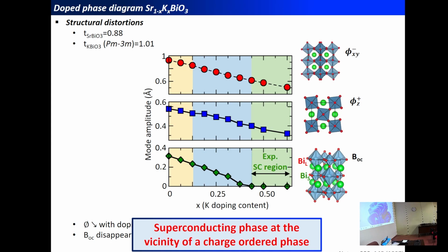But in fact, it's reversed. It's more localized. You would have more electrons on this side than on this side, but it's just because of the sphere, so you would integrate some contribution from the oxygen p states, in fact. So it's not really easy to quantify the charge with the DFT calculation, because there is not a single way to define how the electrons belong to this atom and not to this one. So it's very difficult to track this. That's why I prefer to track the breathing mode distortion, which is directly related to this electronic feature.